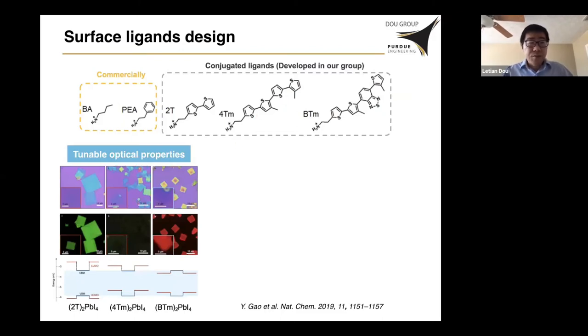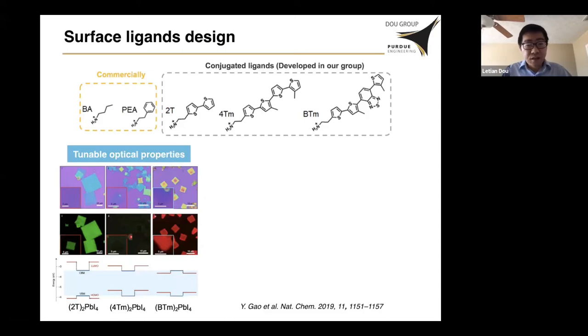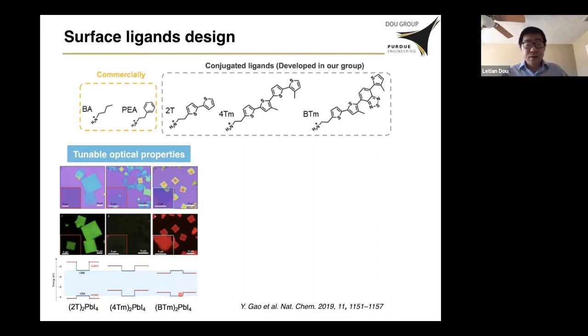Here we show the tunable optical properties of the perovskite by using these different ligands. The optical images show some of those crystals, and the photoluminescence microscope images under UV irradiation show that these crystals emit different colors. All of the crystals contain the same inorganic part — lead iodide — and the only difference is the organic part. These different optical properties are induced by different band alignment. By changing the ligand, we can change from Type I alignment to Type II band alignment, or reverse Type I alignment, between the organic and inorganic building blocks.